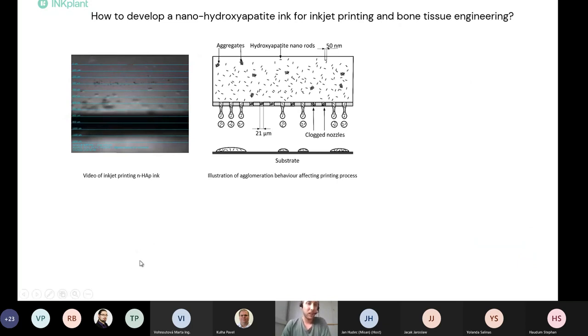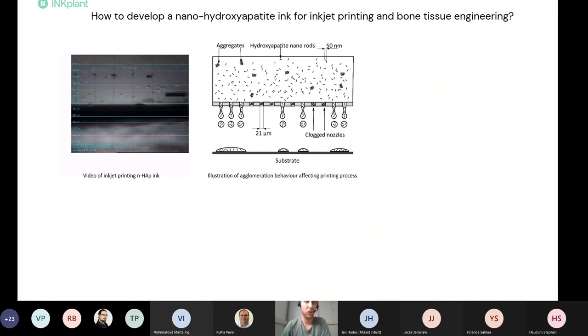I made a small video from a LabJet, a lab scale printer, so that you can imagine how the jetting behavior looks on a printhead. The nozzle diameter in inkjet printing is about 20 to 21 micrometers, and the droplets that you see ejecting from the nozzle plate have a volume of about 10 to 20 picoliter.